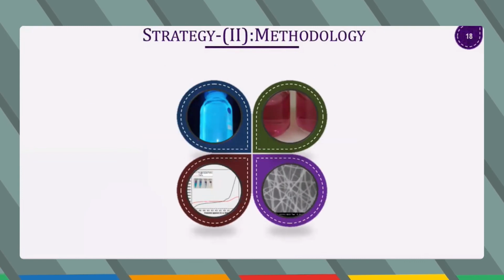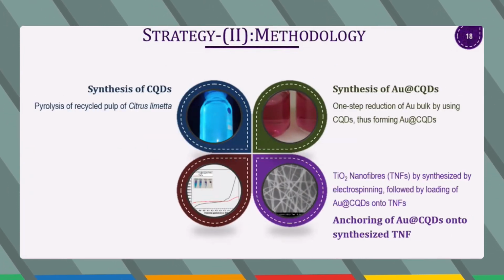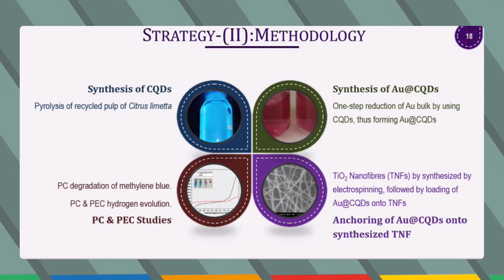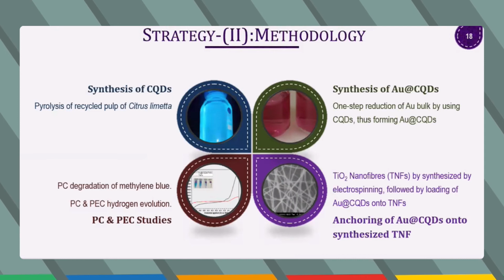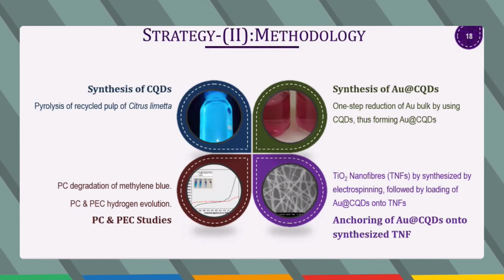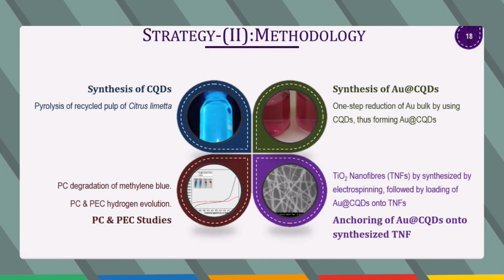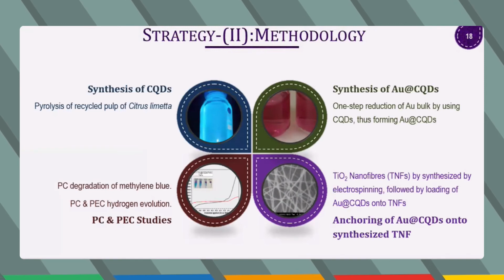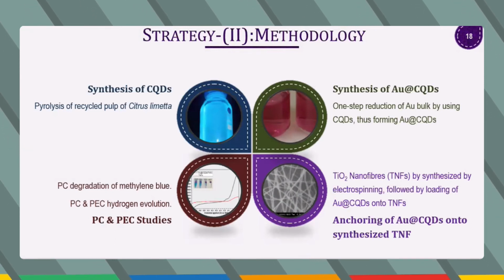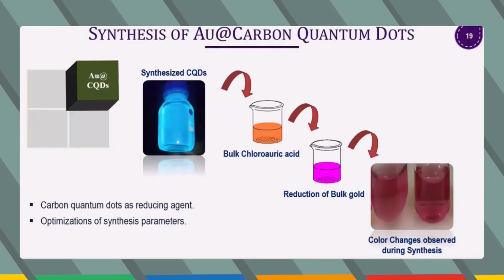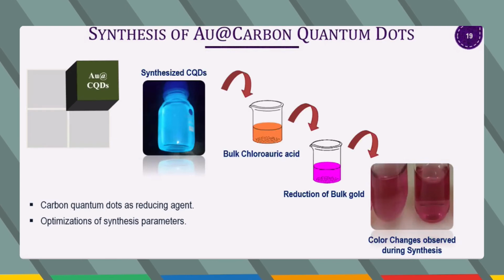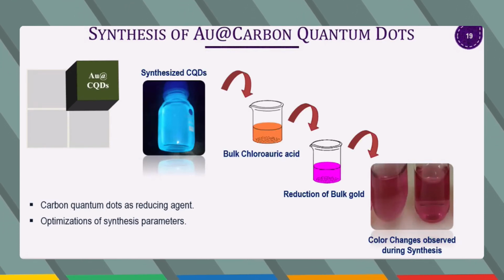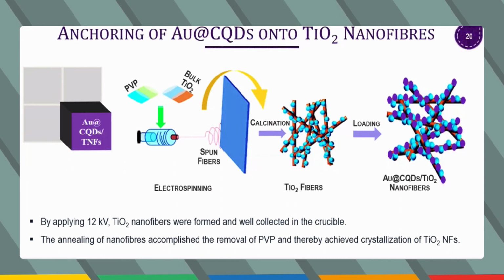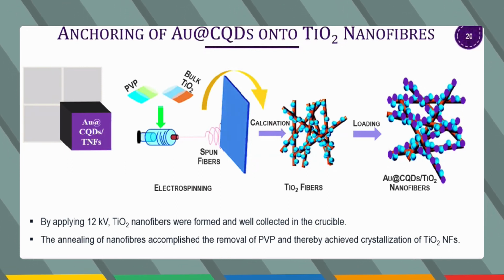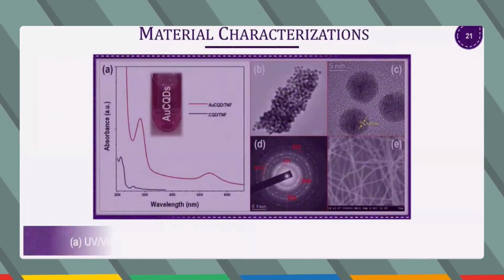Now coming to the second strategy, in which we used the synthesized carbon quantum dots as a reducing agent to synthesize gold carbon quantum dots. This is again an innovative strategy in which we have not used any chemical precursor as a reducing agent, which people normally use in synthesizing gold nanoparticles, like sodium citrate. Here we used the oxidative reduction property of carbon quantum dots to synthesize gold nanostructures. Further, these materials are used to decorate the TiO2 nanofibers, which can absorb the UV spectrum of the solar spectrum. So by designing these materials, we are able to absorb the UV as well as the visible spectrum of the solar light. And again, these materials are well characterized.